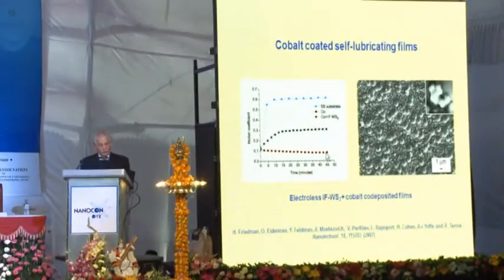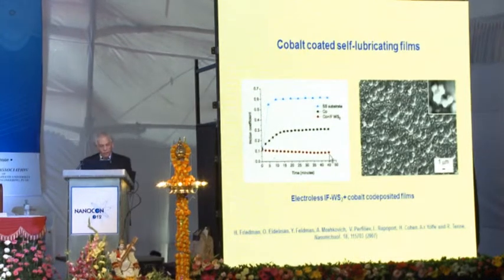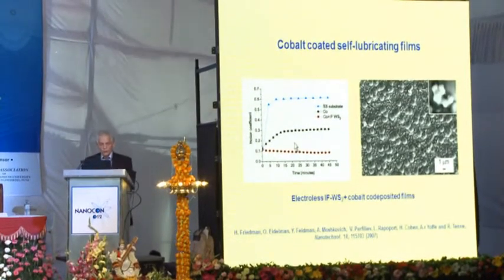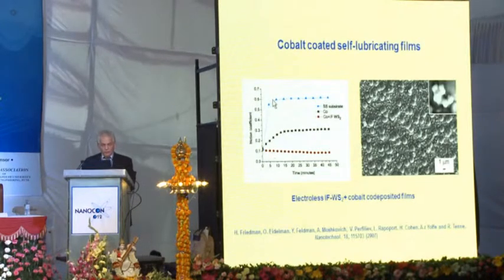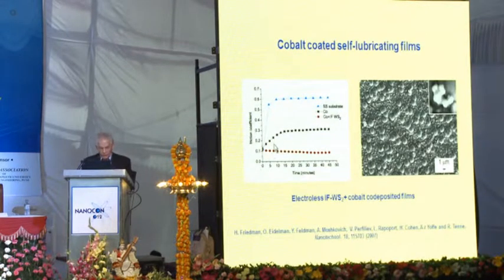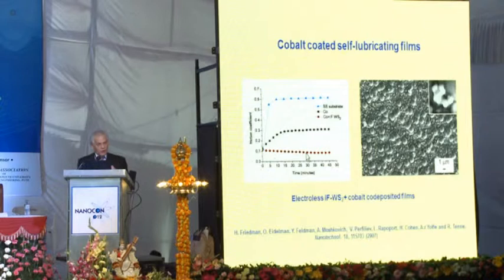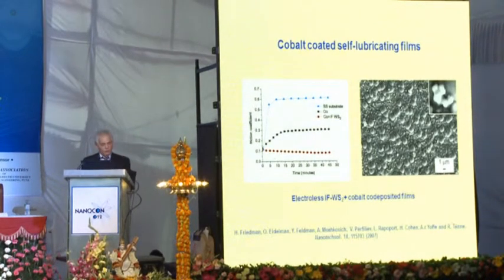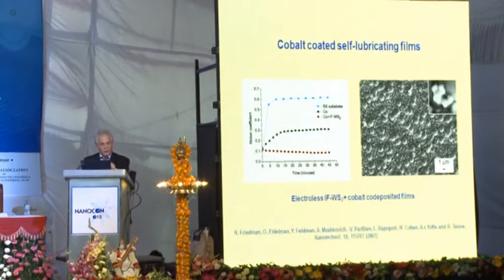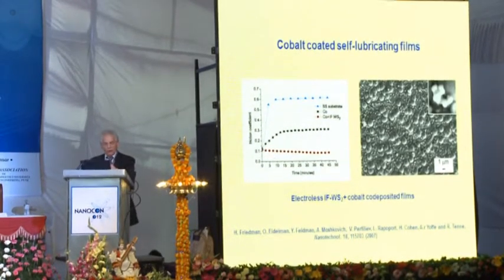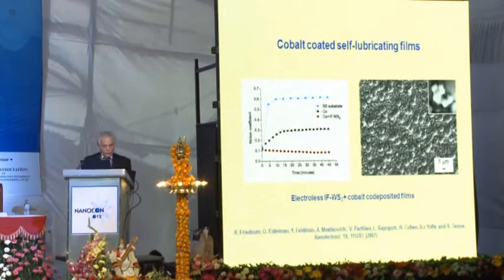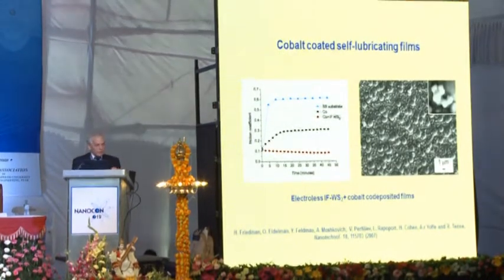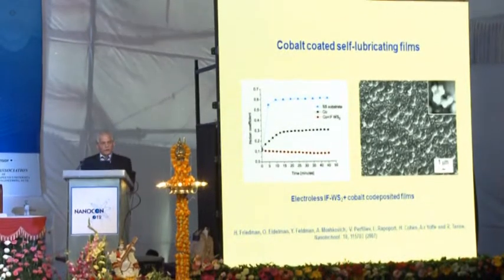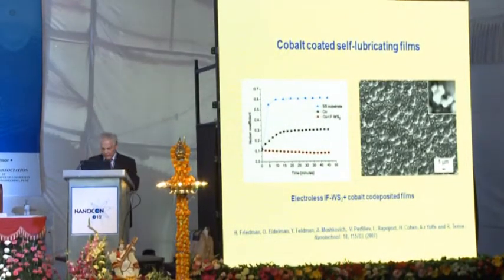The friction coefficient is very low, below 0.1, and goes on for a long time compared to the uncoated stainless steel substrate or the stainless steel substrate with a coating of cobalt alone. So you see a great advantage in impregnating these nanoparticles into this metal coating. This has already been exploited in industrial products, basically in aerospace products. I won't be able to go into details, but nonetheless, there is a big tendency now to use this technology for other applications, and I'll show you one or two examples of this sort of application.